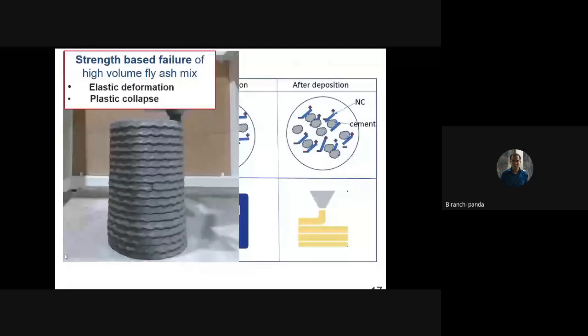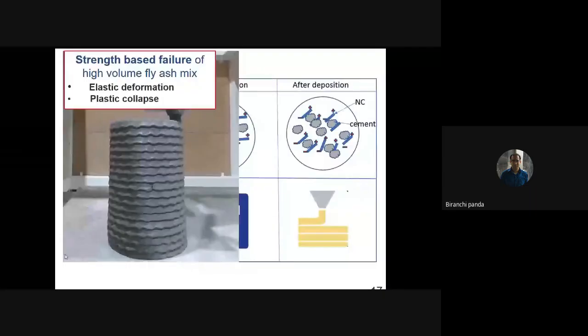When these concrete printed layers started to deform, we classified their deformation. Again, we took the help of strength of materials, because every time we play with a new system or new material, we always try to connect with a fundamental mechanism. It may be from strength of materials, it may be from machine design. So we categorically say that the deformation in the beginning is elastic deformation, but once the material crosses its own yield stress, we expect the material to have plastic collapse.